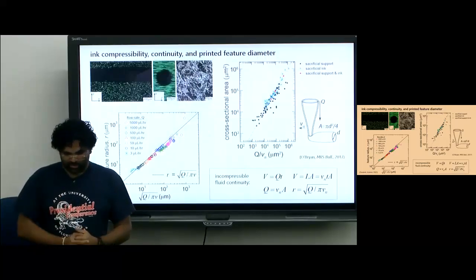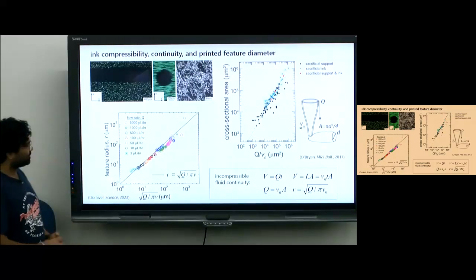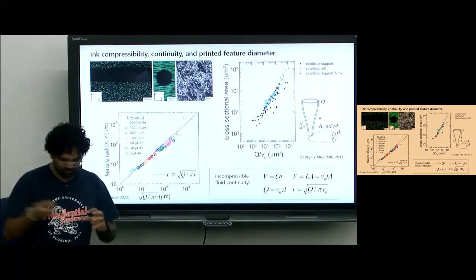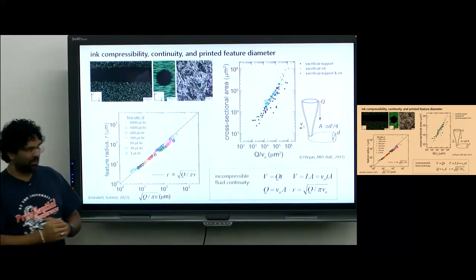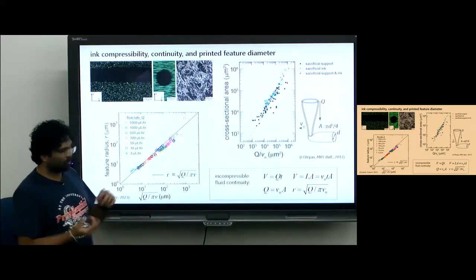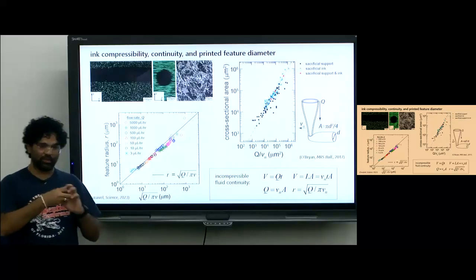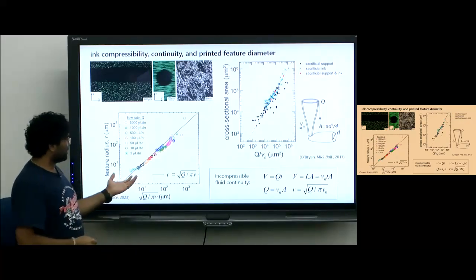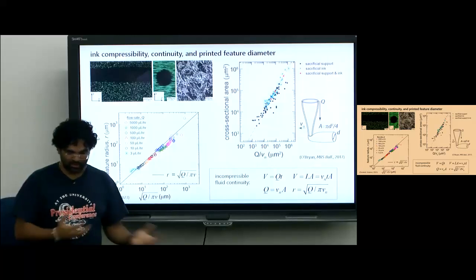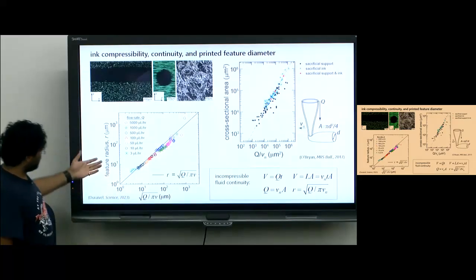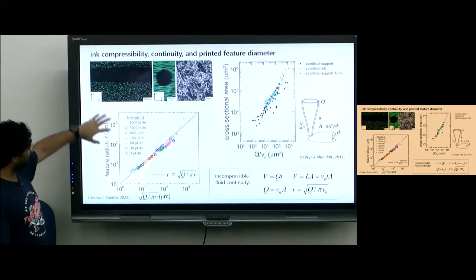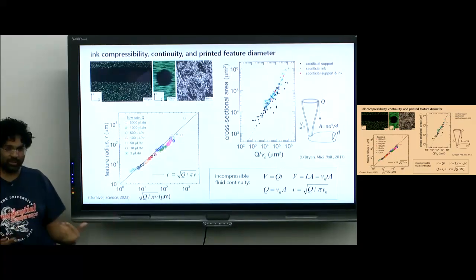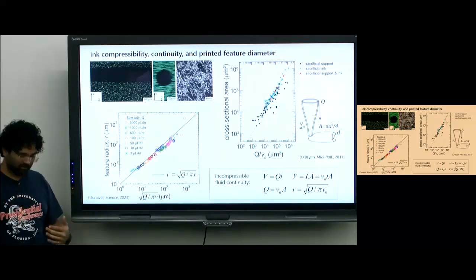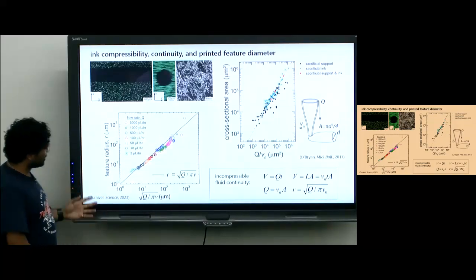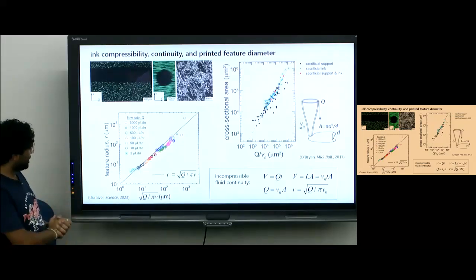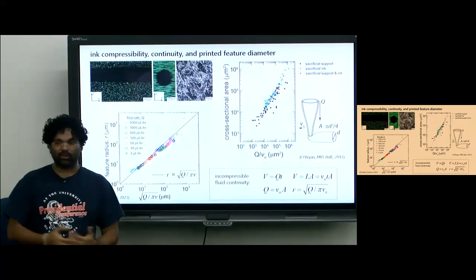In terms of characterizing printing, this is a general way where you would print simple structures like beams, and then from the fluid continuity equation, you can back out what flow rate you need and what velocities you need to move the needle at in order to get the feature size that you're targeting. These are very well characterized at this point in several studies and even in our lab. In this particular case, there was a whole range of flow rates printed, like 3 microliters per hour, which is extremely slow, versus 5,000 microliters per hour, which is fairly fast. And the entire range of printed structures falls within this nice relation, which is just governed by fluid continuity.